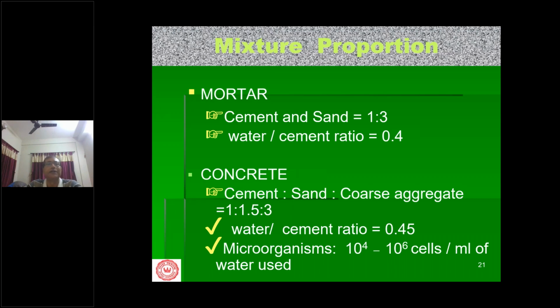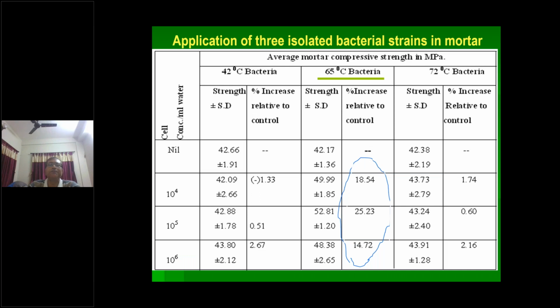Now, after application of these 3 isolated bacteria strains, that is 42 degrees, 65 and 72 degrees, we have different cell concentrations: 10 to the power 4 per ml of water used, 10 to the power 5 per ml of water used, 10 to the power 6 per ml of water used. These are basically the strengths of the mortar, the average mortar compressive strength.